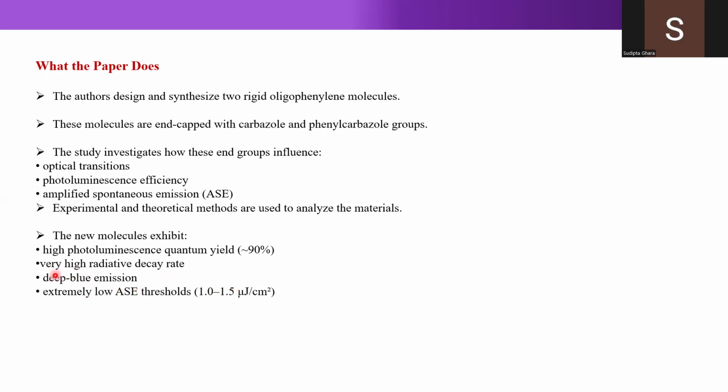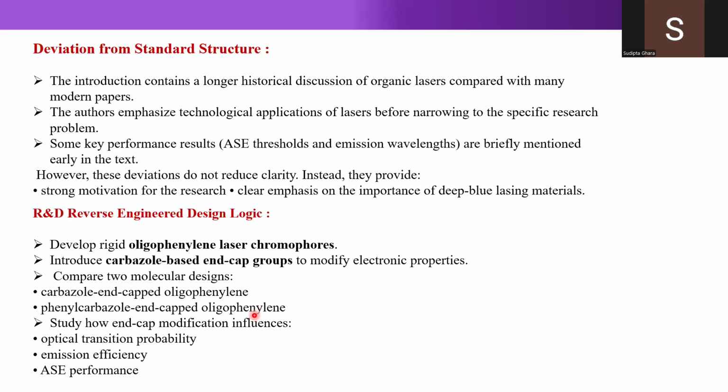And the most important, they got the deep blue emission and extremely low ASE threshold, nearly 1 to 1.5 microjoule per square centimeter. So now, why the deviation from the standard structure? The introduction contains a long historical discussion of organic lasers compared to many modern papers. The author emphasized the technology application of lasers before narrowing to the specific research problem. Some performance results are briefly mentioned in earlier texts.